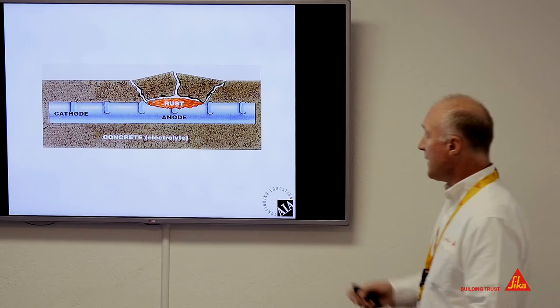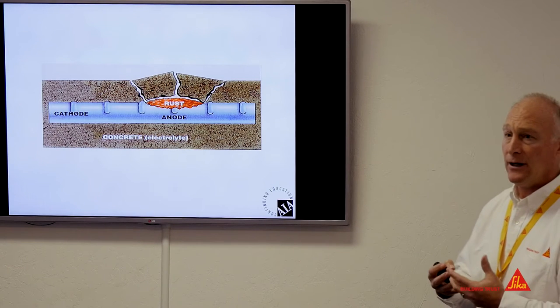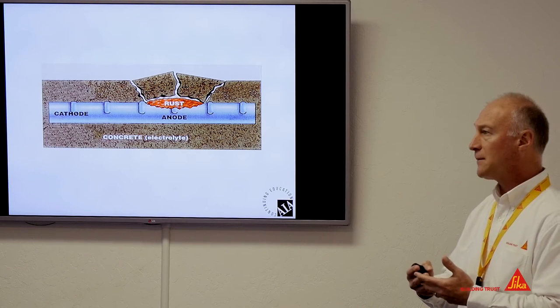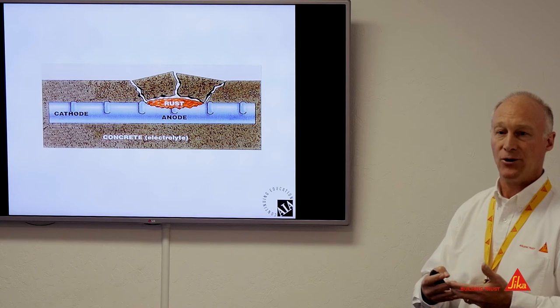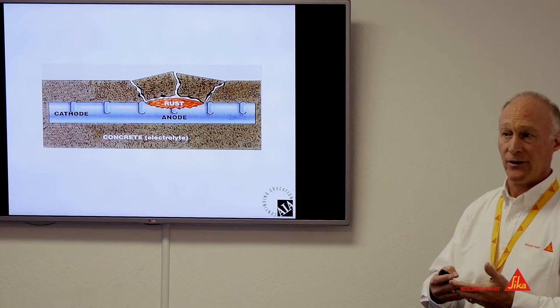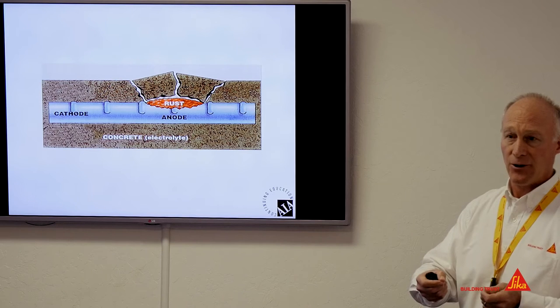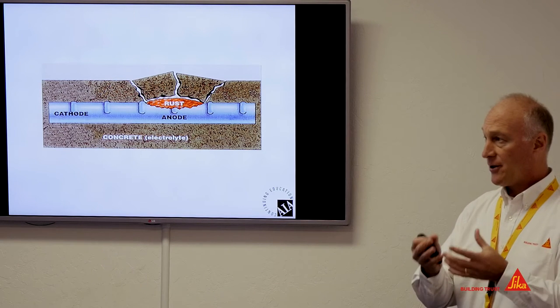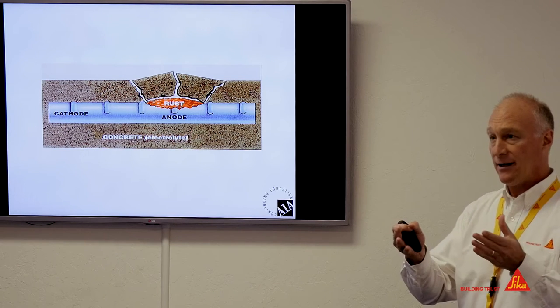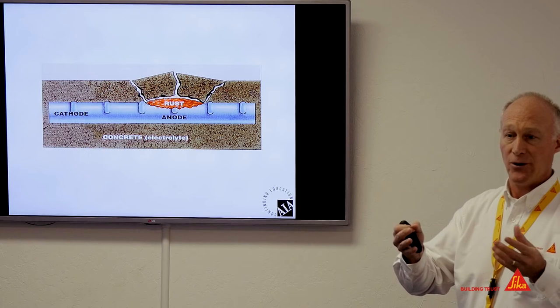And the problem is when that rust develops, the amount of expansion could be 8 to 10 times greater than the steel itself. So that will induce stress into the concrete. As that stress continues, it will crack. And then eventually, as that continues even further, it will spall.